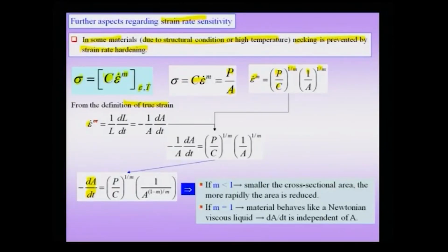If the overall specimen remains without necking, the decrease is going to be small, but because necking takes place in a selected region, there is going to be an increased reduction in area in the localized region, which we call the neck. Putting these two formulae together, the derivation gives dA by dt proportional to P by C power 1 by m, which are all constants of course, and 1 by A power (1 minus m) by m.